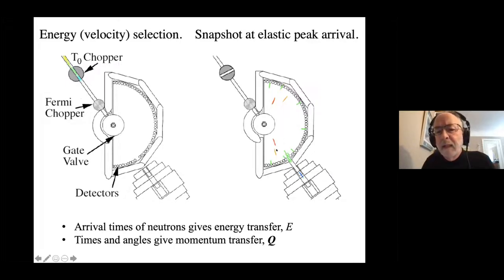The neutrons here have lost a little bit of energy and they arrive later. So the timing tells us the energy transfer to the sample. We also get the angles, not just in this plane of the paper, but plus or minus 26 degrees out of that plane too. And from the angle and the energy transfer, we can get the momentum transfer. So basically what we measure is the momentum transfer and energy transfer, the number of neutrons that undergo that in interacting with the sample.